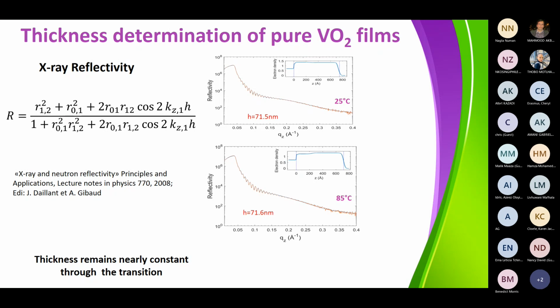And then I didn't speak about that, but the fact that you don't see the fringes at high Q is related to the roughness of the film. So if you increase the roughness, you will decrease the observation of the fringes. And this is what we see here. You can see that we see very well the fringes up to here, and then all of a sudden you don't see them because of the roughness of the film. And this is done in the electron density profile. So you know what is the electron density of the silicon. You know what is the one of the vanadium dioxide. And you can see that the profile does not go sharp at the end. It's quite rounded, and it's rounded because of the roughness of the film.